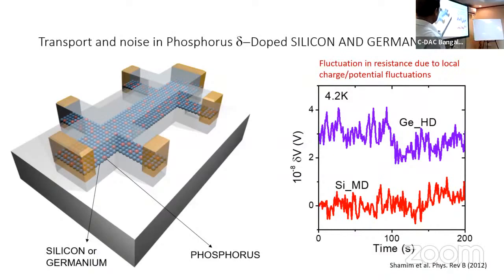And we found that the noise in these kinds of materials is unbelievably low, extremely low noise. This is at 4 Kelvin because we couldn't simply measure the noise at dilution temperature. There was nothing. But at 4 Kelvin or so, this noise came up a little bit, in the order of a few nanovolts at a very large current.